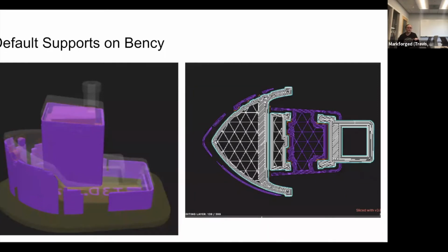So this is a view from Eiger that I took. On the left here, you can see the part kind of in like gray, and the purple is the supports there. So it might be a little bit hard to visualize here, but that kind of purple column, you would not be able to remove this support. So we call this trapped support. It's undesirable, especially if you're printing in metal. With plastic, you can get away with it. You kind of tear it apart, but with metal, you're getting much higher strength material and you're not going to be able to do that.